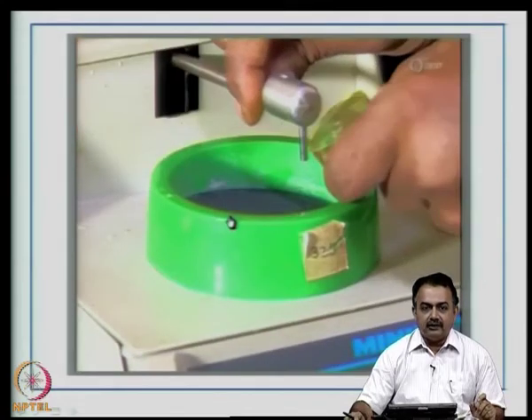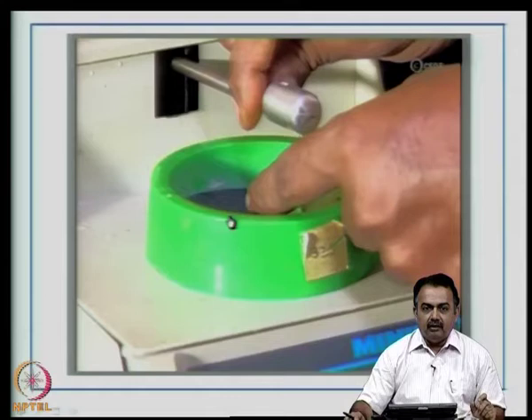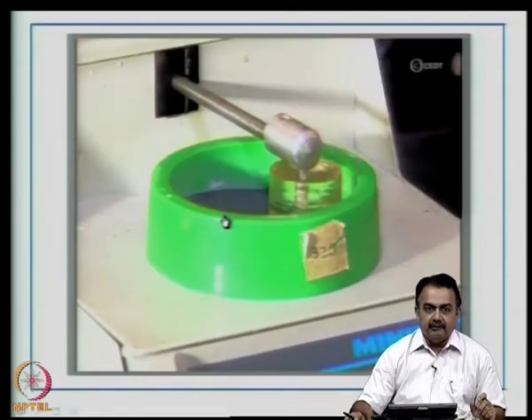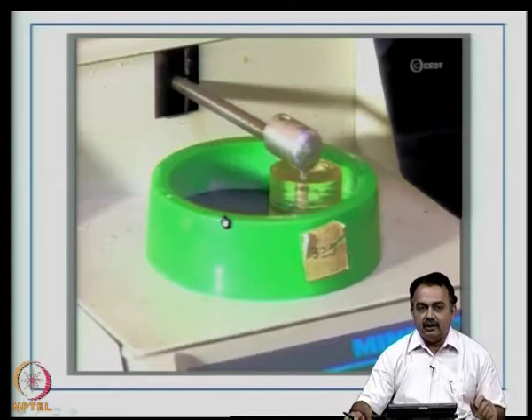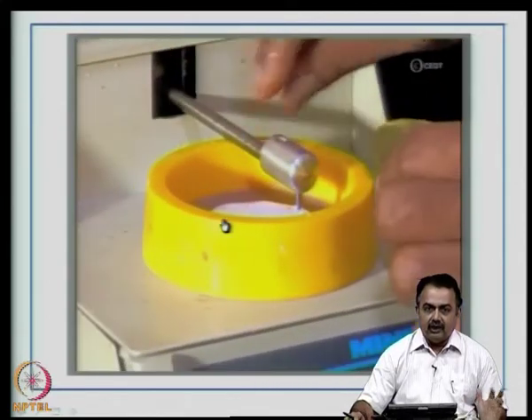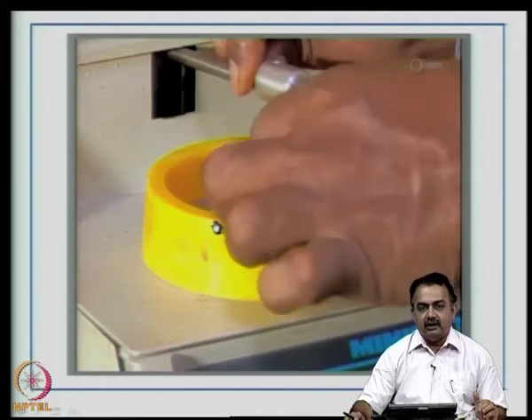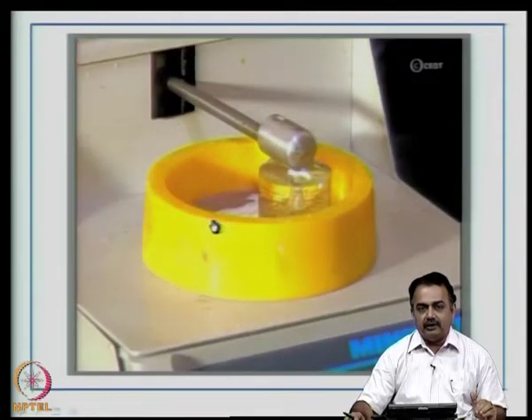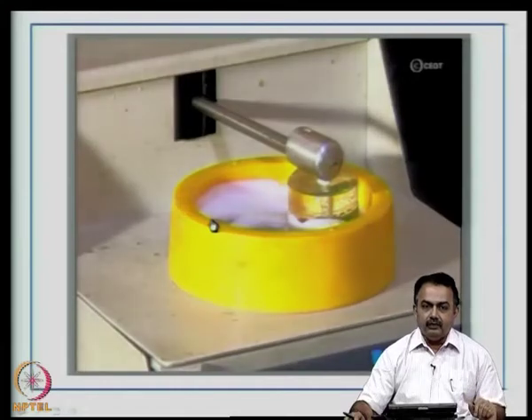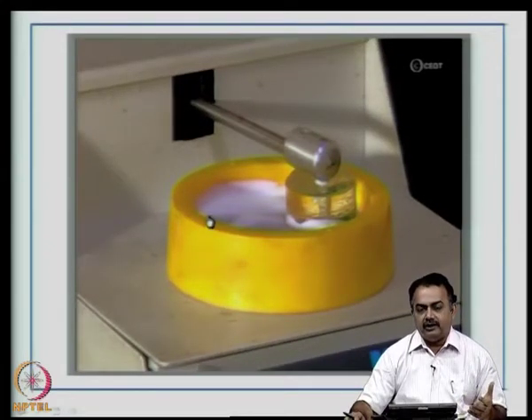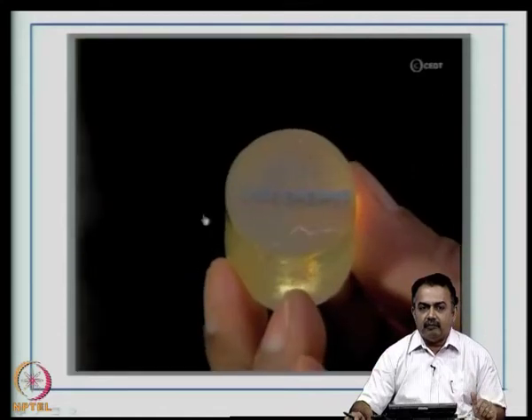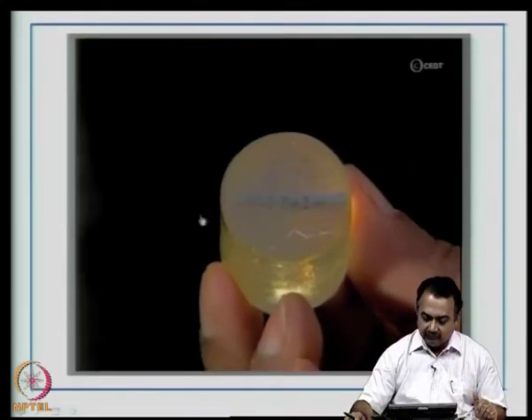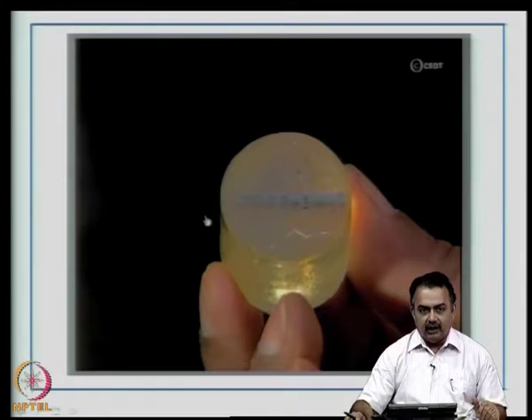So, this container which contains the emery paper also holds the sample that we have just prepared, and then using some kind of a slurry, typically water, and you can see here alumina silica gel is now introduced and then continuously polished at high rates initially, and then slowing down the rate of polishing. Here you can see the surface of the coupon as it was after the coupon was released from the plastic container.